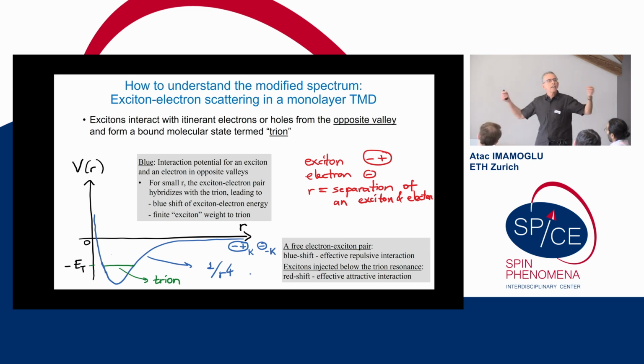Now, as the exciton and electron come together and their separation r is small, they will see the trion state and make virtual transitions to it. Through these transitions, they will hybridize. Just as in any case of hybridization between two states, we normally consider two discrete states that hybridize. Here, it's actually a continuum of states hybridizing with a discrete state, so that's an important distinction. Nevertheless, the effect is that the higher energy state is pushed up while acquiring some bound state character, and that is the origin of the repulsive interactions.